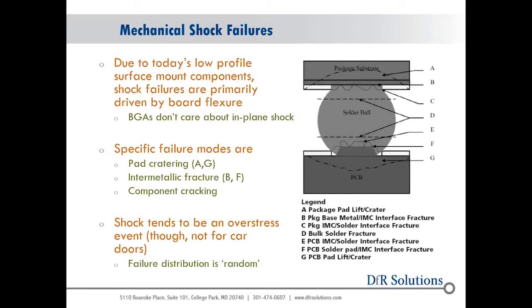It really is more of a bending event, where you get a peeling stress at the corners, which exerts a large tensile load on the solder joint, which can cause it to fracture at the brittle interfaces. When we're looking at the brittle interfaces, we're not talking about failures in the solder ball itself. We're talking about fractures at the intermetallics, on both the package and the PCB side, and about pad cratering, actually breaking the epoxy where the copper is attached to the board. Those are overstress conditions, and you wouldn't expect to see those at 100,000 types of events. You're going to see these very low cycle, large acceleration events, and you're going to cause a brittle fracture where a crack can propagate very quickly through these brittle materials and cause a failure.